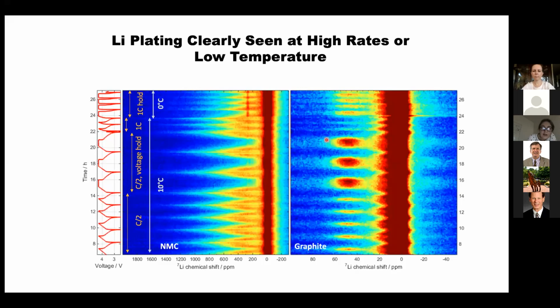But this is now the fun part, when she then started doing things at different temperatures. And so if you go down to 10 degrees and then down to 0 degrees, you can start to see the signal of lithium metal. So this little line here is the signal at 200 ppm where lithium metal happens. And so when you get to low temperatures, the activation barrier of getting the lithium in, coupled with the transport in the electrolyte, is so high that you start plating. And so we can then start looking at the plating phenomena in these materials.